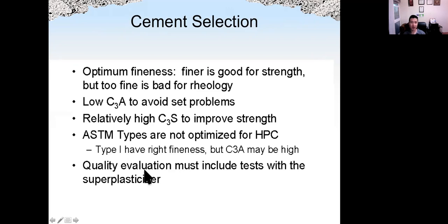For cement, there is an optimum fineness. The smaller the particles, the better for strength, but too fine is bad for rheology, because we need more water to mix the cement paste. With smaller particles the surface area is high, so we need more water to achieve the same workability. If we can reduce the amount of C3A, we could avoid some setting problems. And with a higher percentage of C3S and C2S, we can generate more CSH and improve the strength of concrete. Here it says ASTM types are not optimized for high performance concrete due to the high percentage of C3A, but that is probably not something we can control.